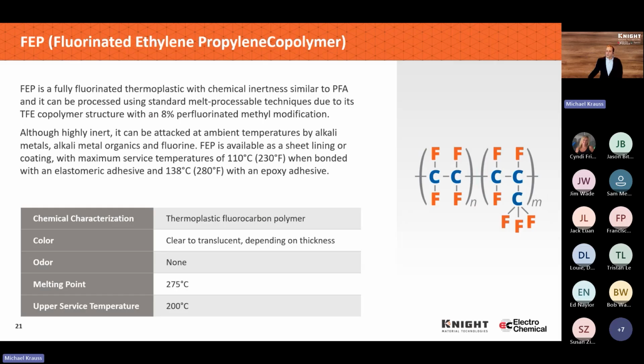Now we'll walk into the fully fluorinated materials. FEP was the first fully fluorinated melt processable thermoplastic. From a chemical inertness perspective, it's similar to PFA. So we started with the polyolefins and the PVCs, then went to the partially fluorinated polymers. When we talk about fully fluorinated, you can see the difference here in the chemical composition on the right side. There's no longer any hydrogen out there. So all of the hydrogen has been substituted with fluorines.